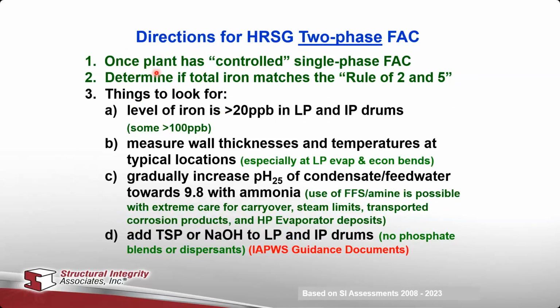So once a plant has controlled the single phase by applying those rules, you want to ask whether the total iron matches the rule of 2 ppb in the feed water and 5 ppb in the drums. The things to look for here very clearly would be that the level of iron in the LP and the IP drums is greater than 20. Sometimes we see this greater than 100 ppb.